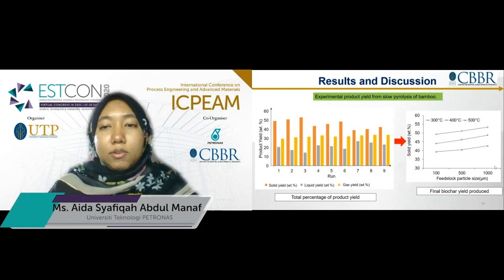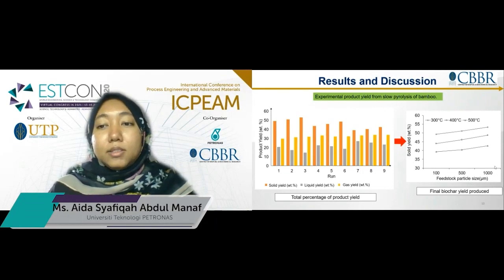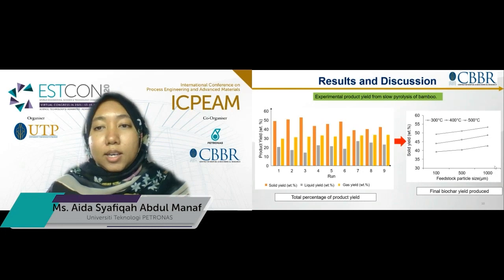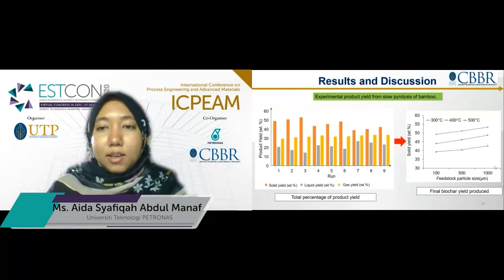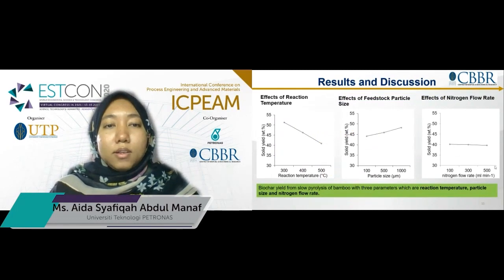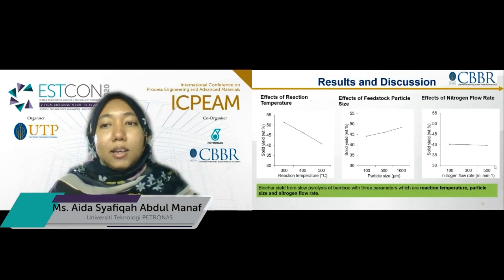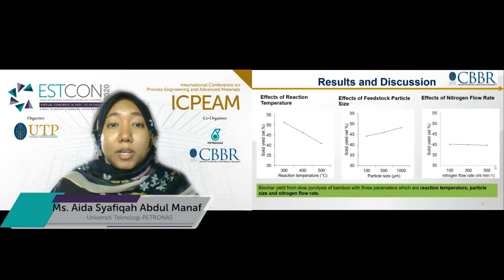So with the graph at the right hand side, you can see that by increasing particle size, we can increase the solid yield with every reaction temperature. However, at this moment, we can see that 300 degrees Celsius will be the optimum, where it has the highest yield compared to other temperature. So these are the graph for 3 parameters, which is reaction temperature, feedstock particle size, and also nitrogen flow rate. As you can see at the nitrogen flow rate graph, it is slightly inclined, but we can see that the yield is not that affected by the nitrogen flow rate compared to reaction temperature and also feedstock particle size.